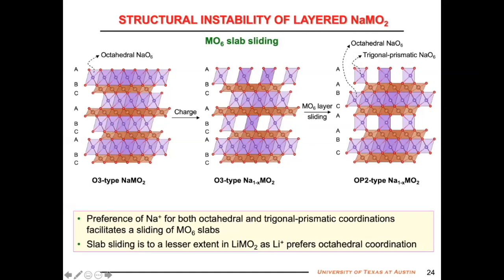Now a couple of slides. So far I talked about lithium layered oxides. There's a lot of work going on with sodium layered oxides. We will have a lot of similar problems as we have with lithium layered oxides. On top of it, we may also have additional complication because sodium prefers both octahedral and trigonal prismatic coordinations. Therefore, they can very easily slide the layers, so you can get O3 to P. P means sodium is in the prismatic, O means sodium is in the octahedral. So those kinds of transitions can happen, which is to a lesser extent in the case of lithium.